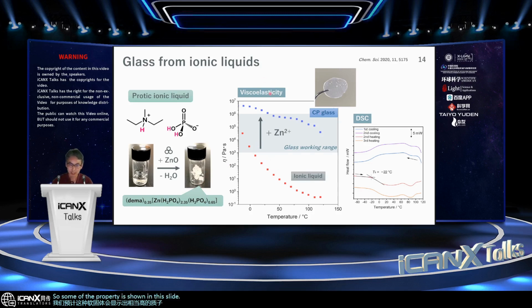Okay, first of all, this is the viscosity. This is the y-axis of viscosity and temperature. As I said, this ionic liquid is a liquid, so we can't deal with it as a solid state. The viscosity is very low, especially above 100 degrees C. But as you know, after reacting with zinc, this obviously forms a solid, and the viscosity goes much higher. But this range is a glass working range, so we can fabricate some membrane or make a good interface with the electrode. So this is a good fit for the mechanics of fuel cell systems.